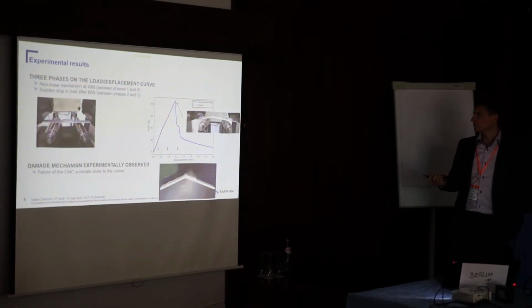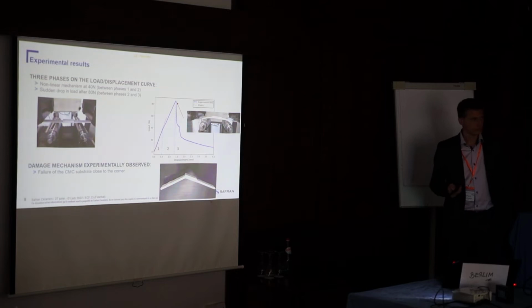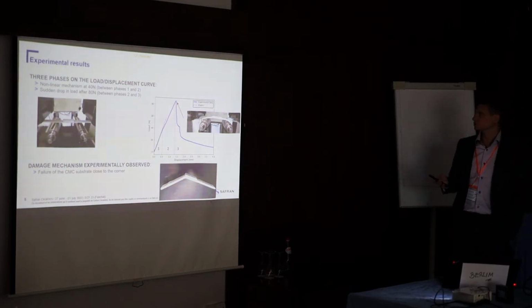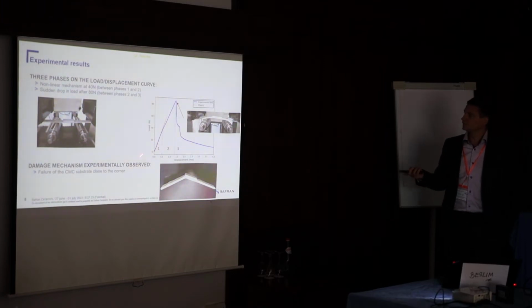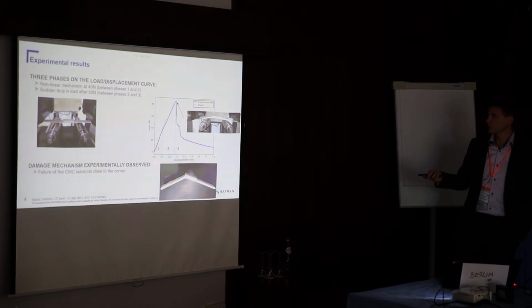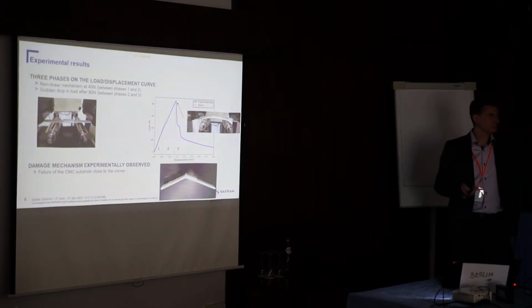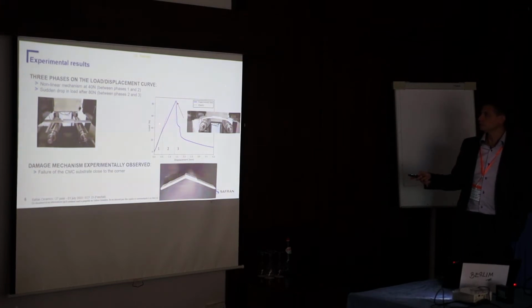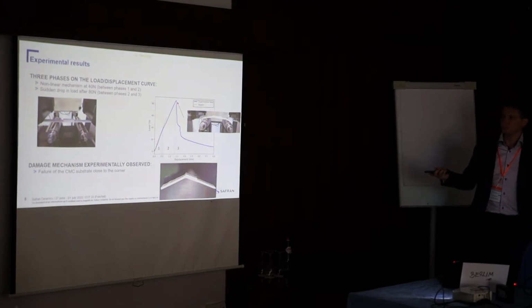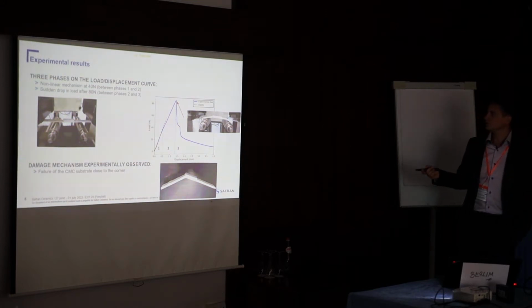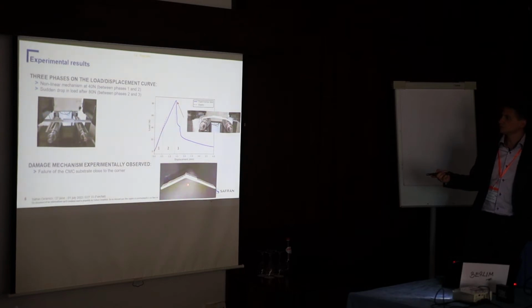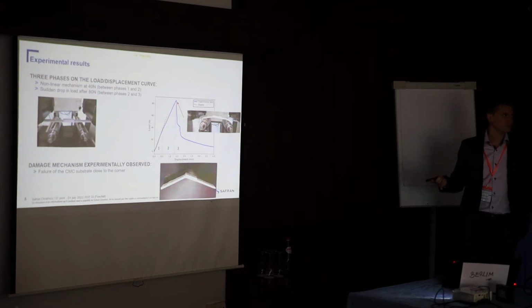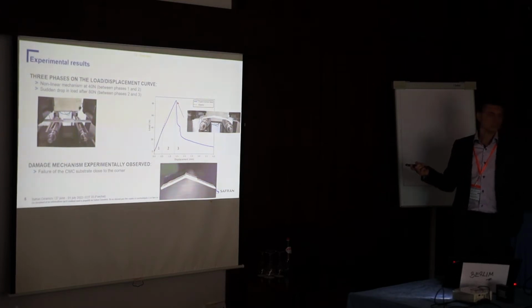We have performed an experimental campaign. Here I show you one example of a test. In the load displacement curve, we have three phases. The first one is an elastic behavior, and then at 40 Newton we have the first nonlinearity, and finally we have a sudden drop in load. When we look at the damage mechanism experimentally observed, we can see the failure of the CMC substrate close to the corner between the bond and the CMC. So obviously we understand why we have a sudden drop in load.